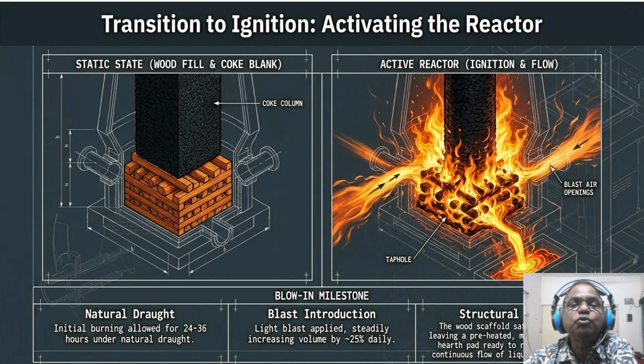We allow the wood to burn under natural draft for 24 to 36 hours before introducing the blast. The wood scaffold safely burns away, leaving a preheated, mechanically intact hearth pad. And this is the ultimate blow-in milestone: achieving a continuous flow of liquid iron and slag without a freeze. By following this hearth timbering protocol, you have engineered a path for success. You are no longer just lighting a fire, you are stabilizing a mammoth vessel, the reactor, the blast furnace.